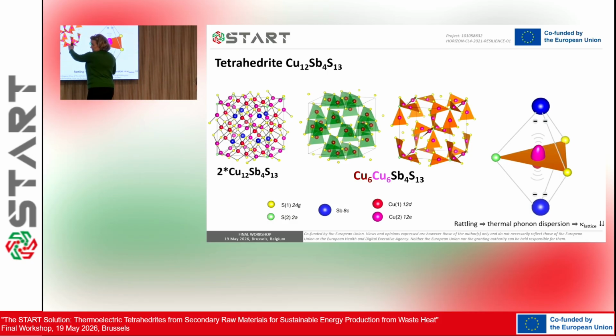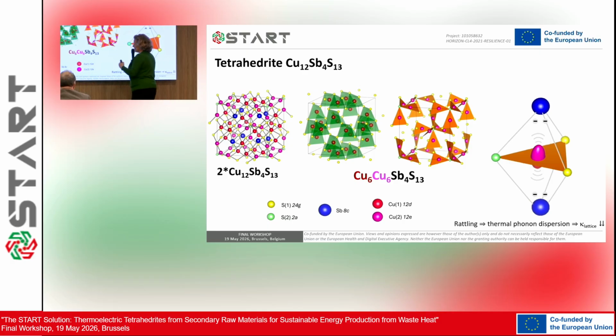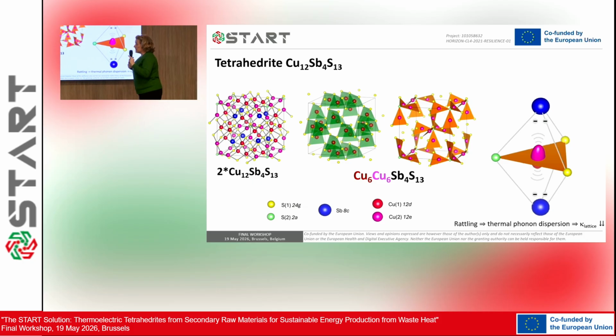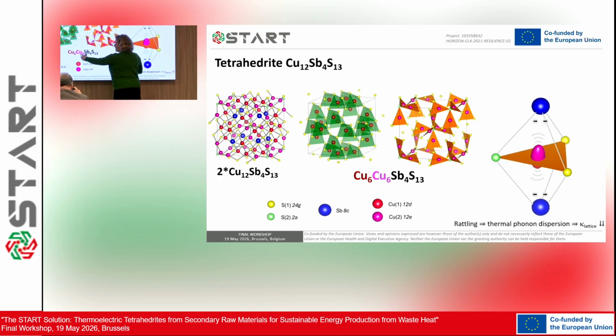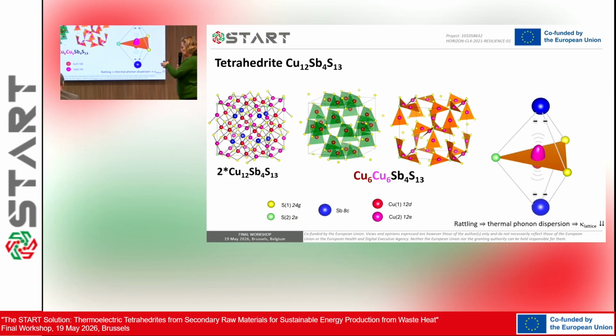We don't want to replace this. The structure doesn't allow you to replace this. It only allows you to replace that. And even so, only about 2, because 2 atoms of this 6 copper. Because this copper is monovalent, so plus, and when you replace with other atoms, like nickel or iron, it's 2 plus. So you can't replace, there's a charge imbalance that the structure doesn't allow you to replace a lot of those coppers. Typically, the maximum is 2 atoms.